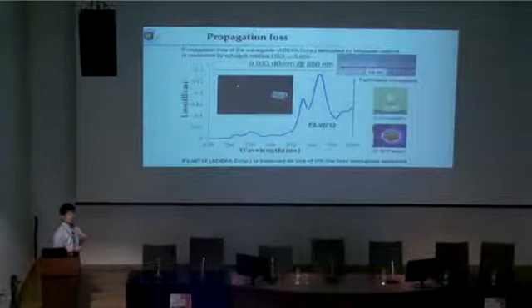Then first, this is the optical loss spectrum. At 850 nanometer, 0.033 dB per centimeter is available. And as I mentioned, because the graded index core is not using the total internal reflection scheme, we could decrease the excess scattering loss at the core cladding boundary.